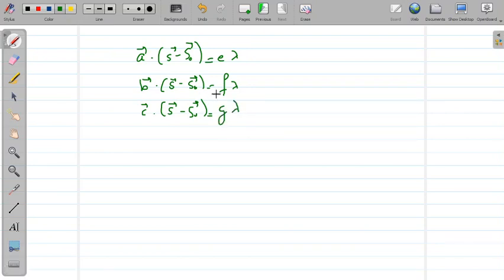The meanings of all these terms are known to you, and these three equations are together known as the Laue equations. So if these three equations are satisfied by a beam of rays, then that ray will correspond to maximum brightness, or that ray will give you a diffraction pattern of maximum brightness.